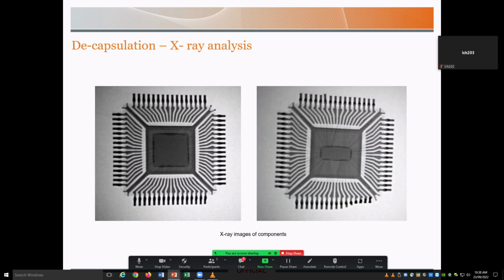The first step before we jet etch is to X-ray our package. This is useful. It shows us the location and the size of our chip within the package. We can also see some wire bonds here if you look closely, especially with a high resolution X-ray. If you can see that some of these wire bonds are already broken, it means that during the jet etching process, you can decapsulate just a specific area and focus on where that failure has occurred.